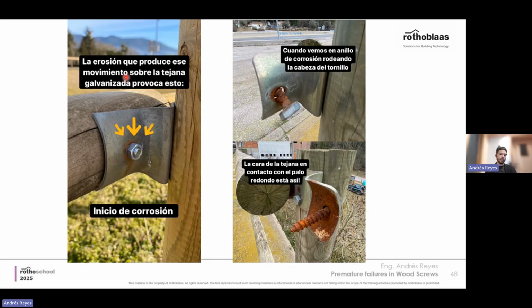But coming back to the importance of timber corrosion, what you see here, I'm sorry about the Spanish, is from a consultancy that we dealt with, and it helps to illustrate how powerful timber corrosion can be. So here in this case, atmospheric corrosion is not an issue, as you see here. I mean that in general, the bolt, the nut, the fastener, and the plate are doing well. But when you take out the wood and see it from below, you see that this is a matter of wood corrosion. See how the internal part of the screw is affected, and if there is material susceptibility and the force generated by the load of the wood, the conditions are met for hydrogen embrittlement to happen.